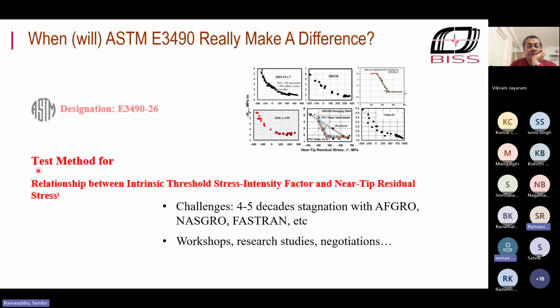My personal opinion is, go by the property as it is determined. Because when you're determining it, you are always determining it on a particular material thickness, so you're going to use the property for that material thickness. If you have a thick component, you don't have to worry. Just assume plane strain conditions. If it's a thin component, then you're worried about long crack behavior, because these could be structural elements. And over there, the condition of the stress state is dictated more through parameters like crack closure, because of the surface conditions that dominate. So that is likely to have a big effect.